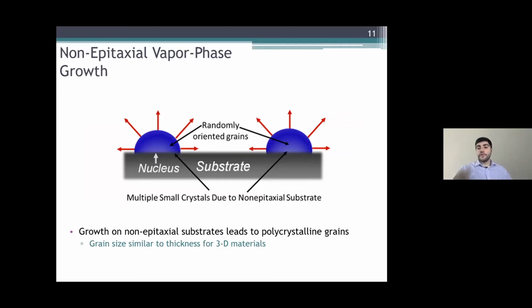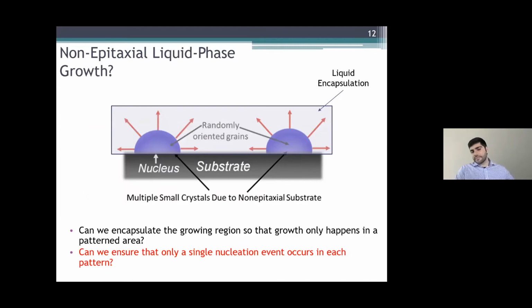And so if you want nuclei that are spaced by 10 microns, in general your film is going to be 10 microns thick before they merge. Now, what we were saying is, what if we encapsulate it so we control how thick these can grow, but still let them grow out laterally, and then modify the growth conditions such that you only get a single nucleus in whatever area you want. That way you can define an area, grow the material such that you only get a single nucleus, and then have a single crystal domain of some size.